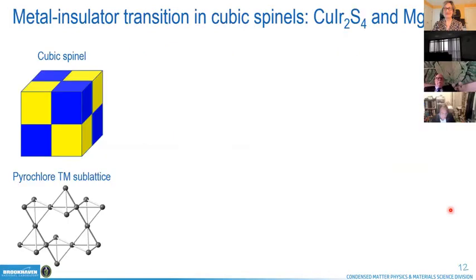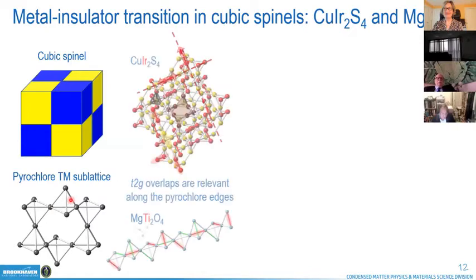Good. So, as I said, they have a cubic spinel structure, which has this block form. And underneath, there is a pyrochlore sublattice of corner-sharing tetrahedra of transition metals, whose d orbitals happen to overlap along the edges of this regular high temperature cubic sublattice. As you go to the low temperature regime, you get all this complexity.